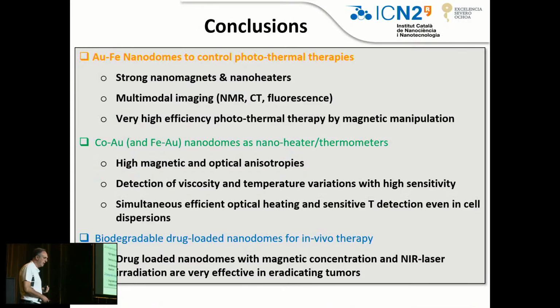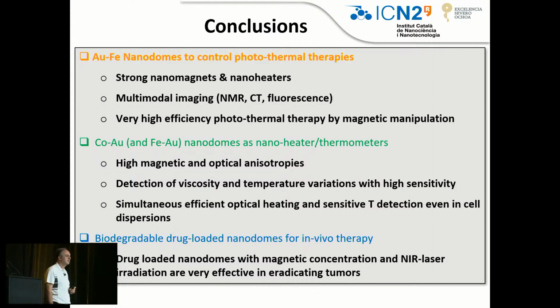So to conclude, I hope I have convinced you that we have been able to grow some strong nanomagnets, which are good nanoheaters, which can be used for multimodal imaging, with NMR, computed tomography, and fluorescence. And they have a very high efficiency in photothermal therapy by magnetic manipulation. I've also showed you that we can design nanodomes with high magnetic and optical anisotropies, which can be used to detect viscosity and temperature changes with very high sensitivity. And we can simultaneously use the nanoparticles both to heat and to measure the temperature, even in cell dispersions.